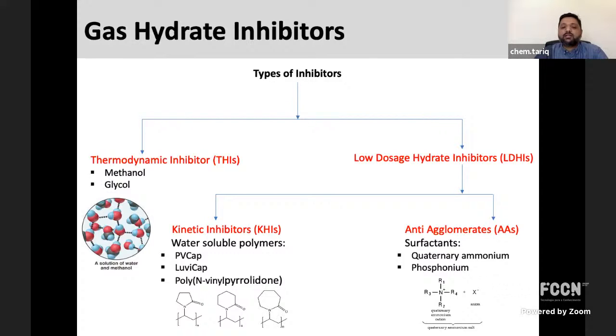That's why, in the last two decades, low dosage hydrate inhibitors came into existence. Low dosage inhibitors can also be divided into two types: kinetic inhibitors and anti-agglomerates. Kinetic inhibitors are generally water soluble polymers, such as polyvinyl caprolactam or polyvinyl pyrrolidinone. They will not shift the boundaries of hydrate formation and will not stop the hydrate formation. Instead, they will reduce the rate of formation.